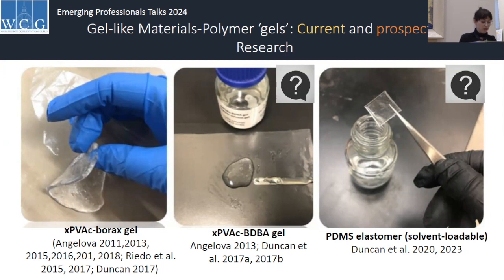Early explorations with these materials showed that they behave unpredictably, especially when incorporating a range of organic solvents, and that's primarily what my work is about. This research arose in response to the need to identify trends in the physical working properties of these materials so that we can better understand how to formulate them successfully for conservation treatments and make them practically accessible materials. The good thing about the PVA BDBA gel is that you can develop this without any water. So I'm looking into that for creating a gel that is really good on highly water-sensitive surfaces.